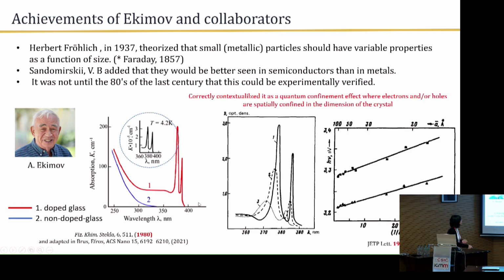One year later, he published another paper in which he saw that these absorption peaks in the absorption spectra moved, blue shifted, with the different treatments that he performed on his glasses. So he performed different treatments, heating and annealing processes, and then he observed how these peaks moved and blue shifted. And then he evidenced that this shift is related to the size of the particles that were embedded in the glass. This was done by small angle X-ray scattering, and in this way he evidenced the presence of these small colloids in the glasses.